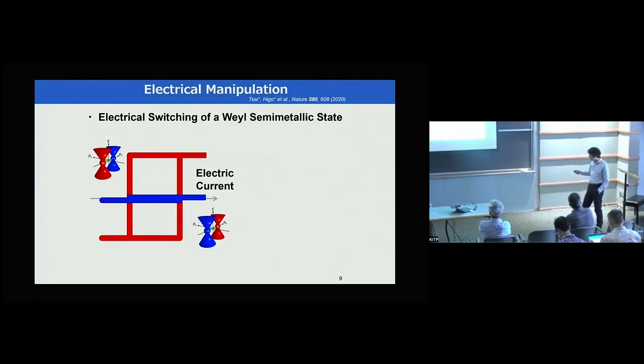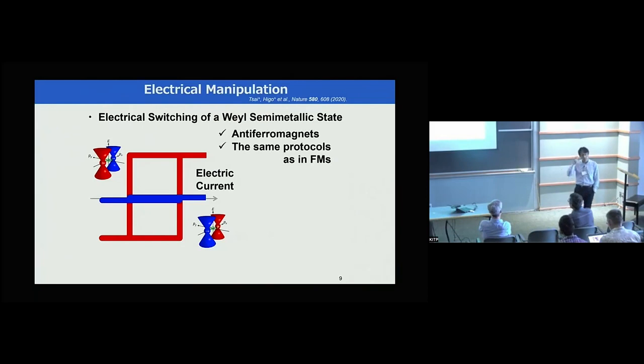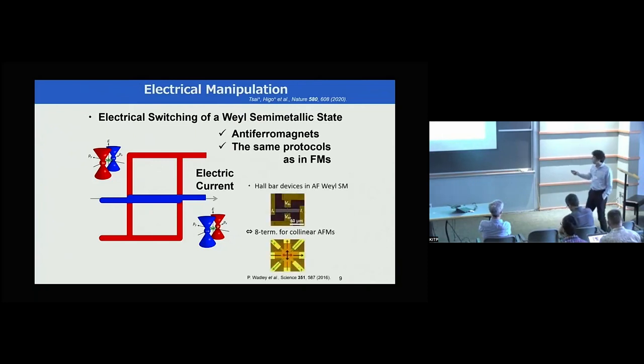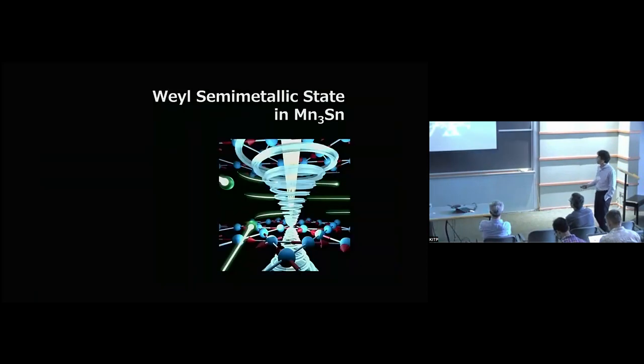We didn't expect this, and we experimentally discovered that it was possible to electrically manipulate this Weyl semimetallic state, the first among such systems, made in an antiferromagnetic system. It actually turned out to be so simple to manipulate this just using existing spintronics technology developed for ferromagnets. For example, you just use a Hall bar to manipulate the magnetic texture of this state, in comparison with many more complicated structures developed for collinear or maybe recent exciting altermagnets.